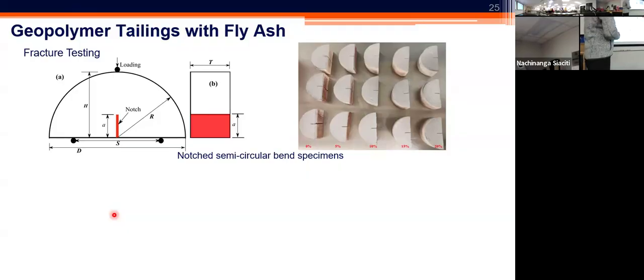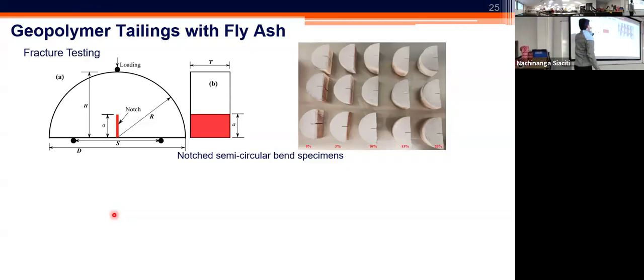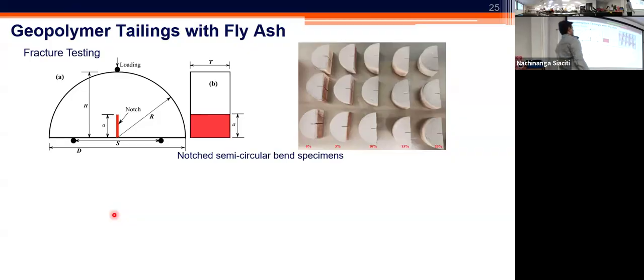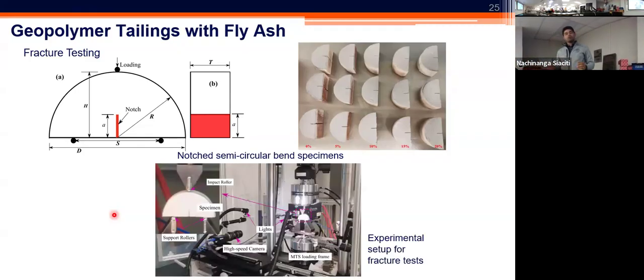What we did in this scenario was a 3-point bending test on semicircular specimens. These specimens were cast the same way as before. We put them on 2 rollers and then apply the load at the top. This facilitates the formation of mode 1 fracturing from the tip of the existing notch. Think of this notch that we artificially introduced in our sample as your windshield chip. That's the point of concentration and initiation of the cracking. With this mode of loading, we can promote the fracturing and evaluate how much force it takes, and what the characteristics of the fractures are as they're generated. We also applied a technique called digital image correlation.